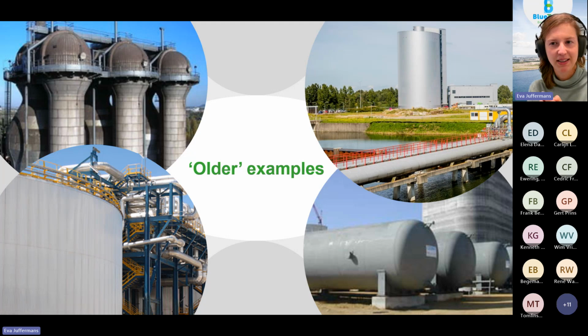On the top right, you can see a tank water thermal energy storage. This one is located near Amsterdam. It is owned by Vattenfall, and it uses water up to 125 degrees, so under pressure, to supply heat for a district heating network.